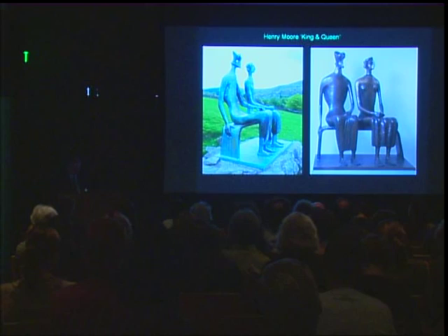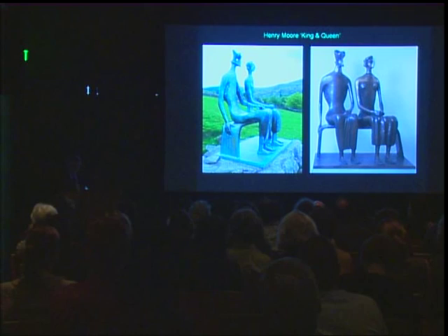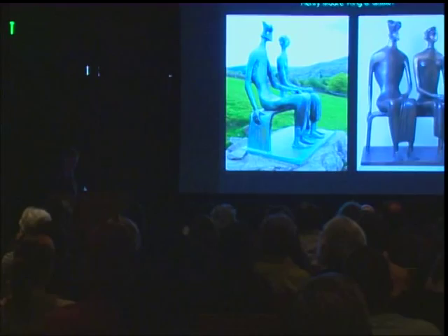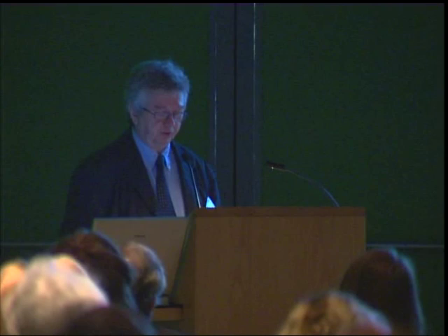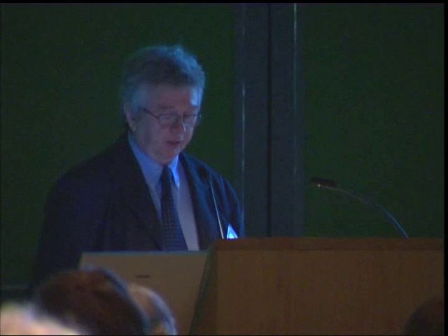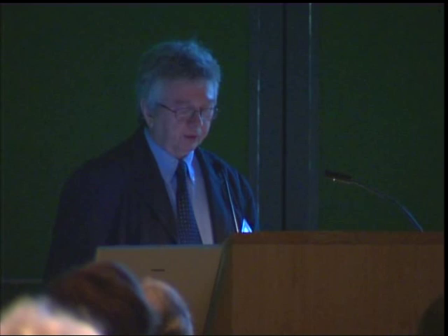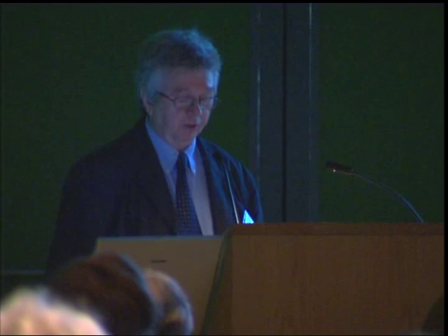Cleaning and maintenance decisions are also key factors in the long-term appearance of outdoor sculptures. Cleaning is one of the most easily misapplied conservation techniques, which can lead to large collections of bronzes acquiring a uniform oxidized finish that masks and possibly destroys variations that were present when first made. In central London, bronze statues were, for many years after the Second World War, government maintained. They all acquired a uniform black patina due to the identical cleaning and oiling treatment applied to them without regard for the bronze's original appearance.